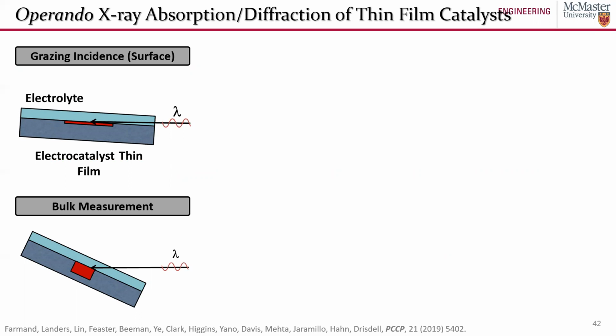One way to do that is to do measurements in what's called grazing incidence configurations. Essentially, you illuminate your catalyst thin film with X-rays, but you illuminate it at a very glancing angle. So it just glances off the very surface of your catalyst, and that can give you information about the near surface region of your catalyst. This is in contrast to conventional measurements where you just blast your thin film with X-rays. It can be perpendicular or at any other angle, and you're essentially illuminating the bulk, and the spectra that you're going to get is going to be a bulk averaged spectra of your materials. So we needed to design a reactor that we could get X-rays in at very glancing, very grazing incident angles.